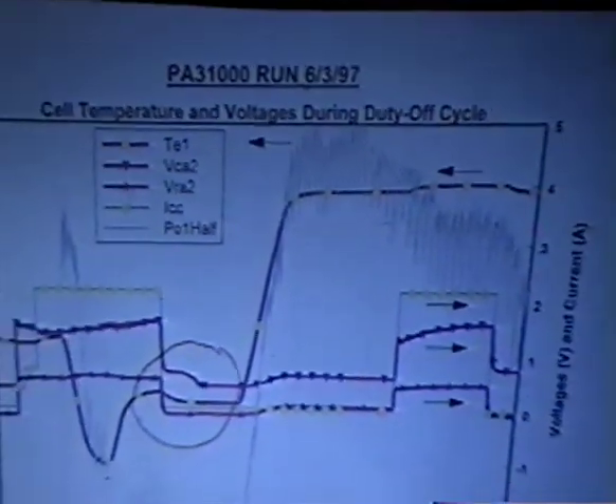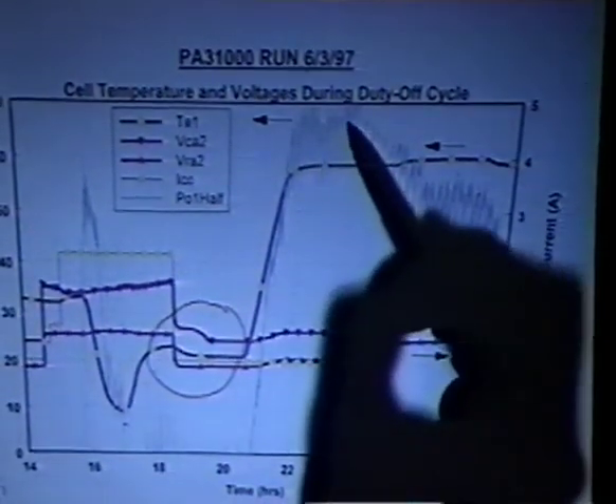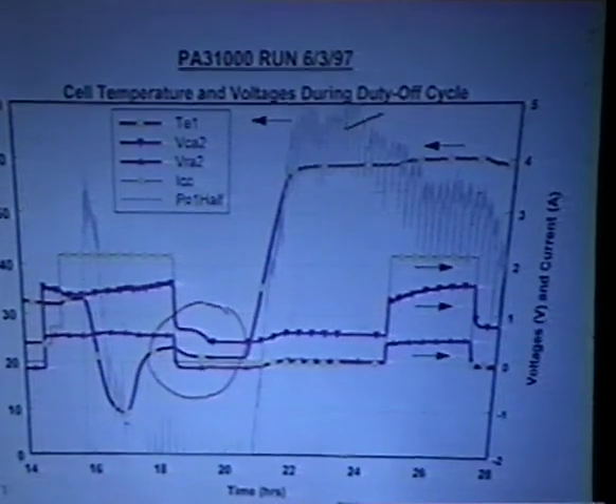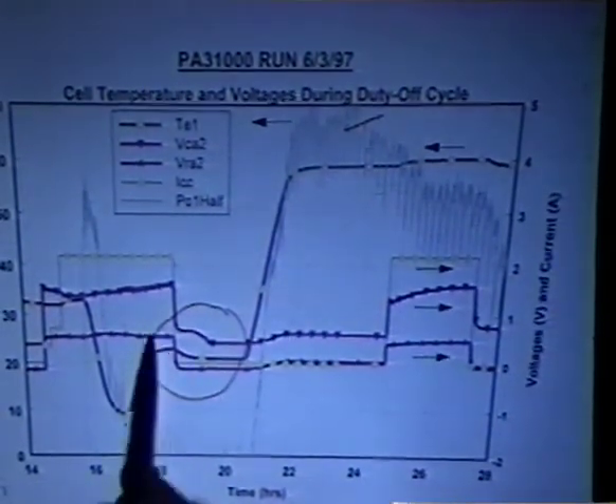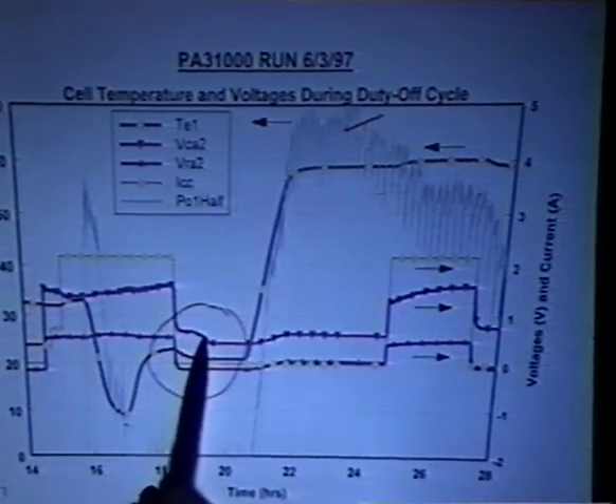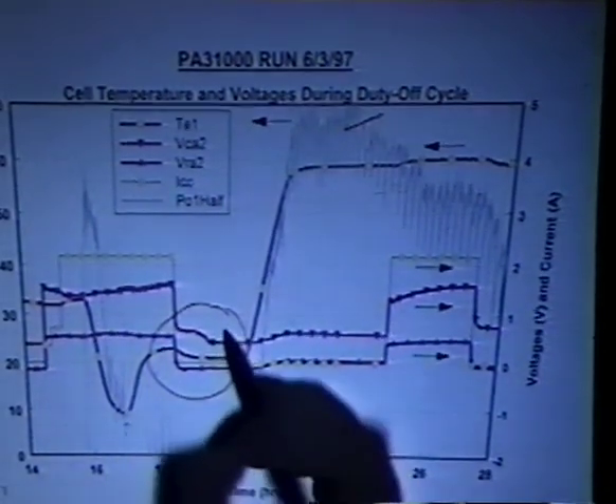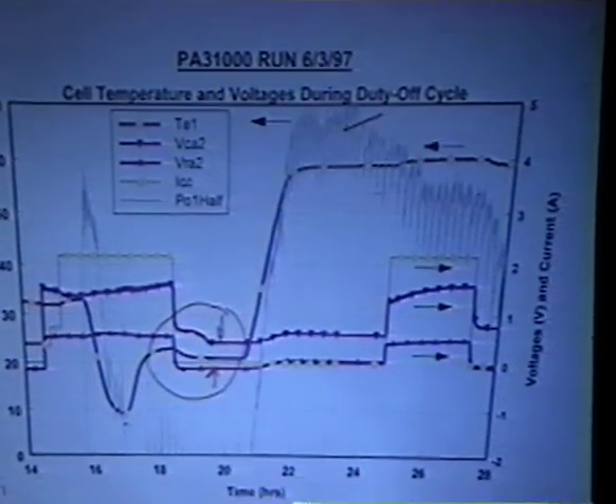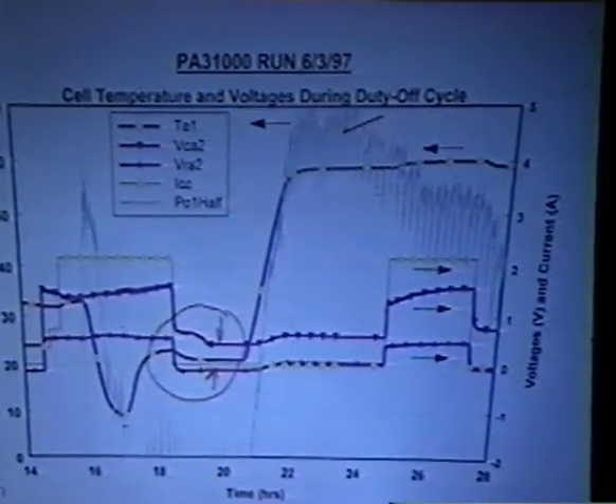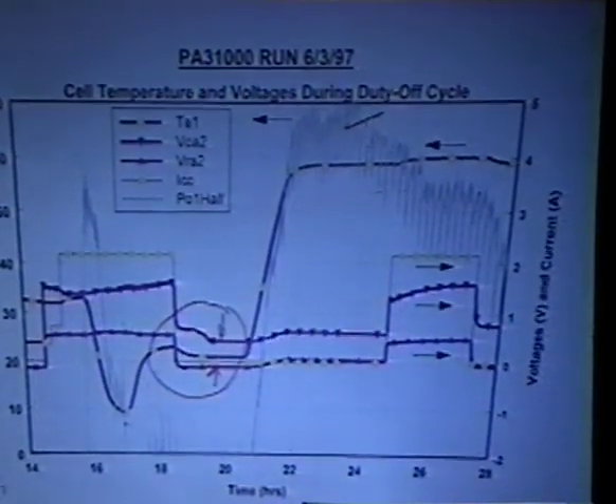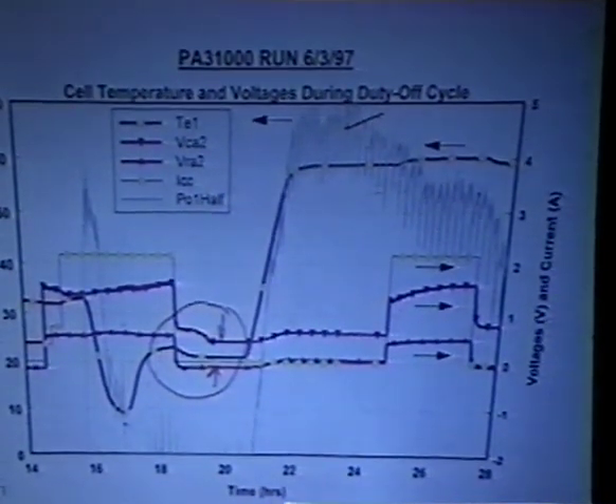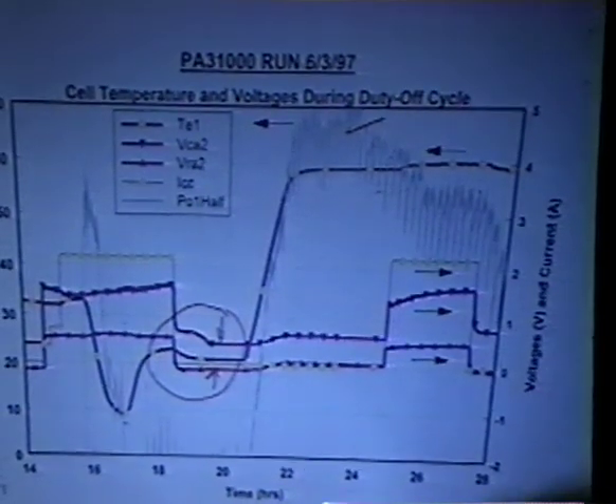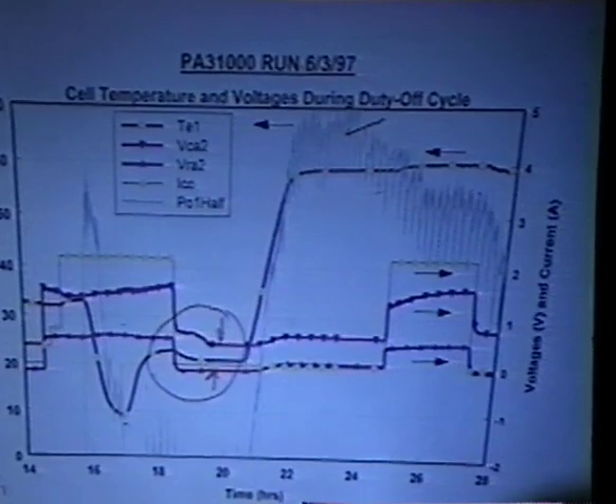And this particular first run, the one that actually made the heat after electrolysis, what I want to focus on is this region right in here. Again, it's a blow up of the region where the power begins to form. And this little plot here is the actual power that shows up. Again, it's on the order of 100 watts total. But right in here, when these voltages drop, what I found is that this distance, this number right here between those two voltage levels, is about plus 0.6 volts, 0.6 to 0.65, is when the power shows up.